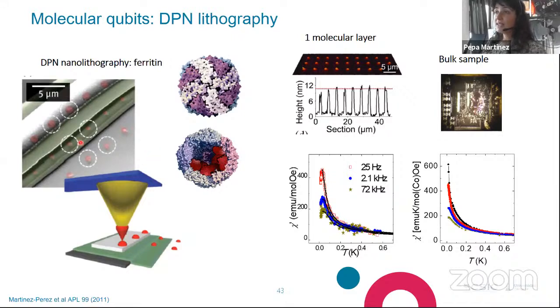We applied a very interesting technique called dip-pen nanolithography to deliver monolayers of these proteins above the surface of our sensor. This can be verified in this AFM image, where you see that the particles are indeed arranged in a monolayer. Our measurements down to very low temperatures show that the properties of the proteins are kept down to very low temperatures, showing the superparamagnetic blocking of the susceptibility as they do when you measure a bulk sample.